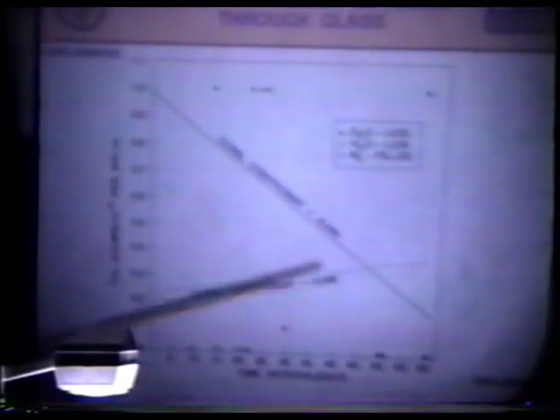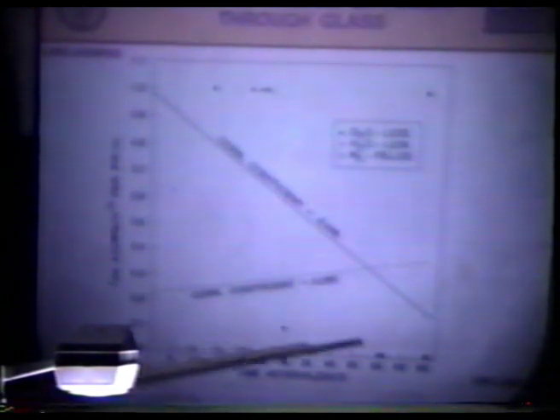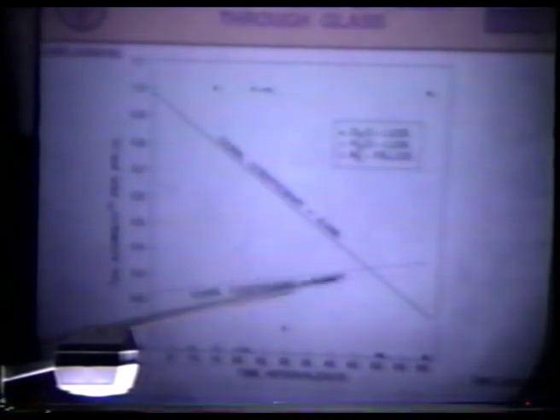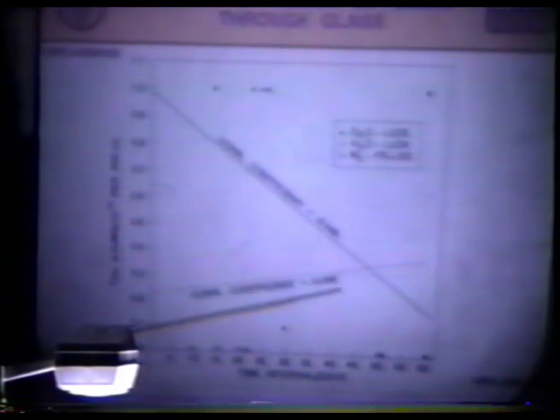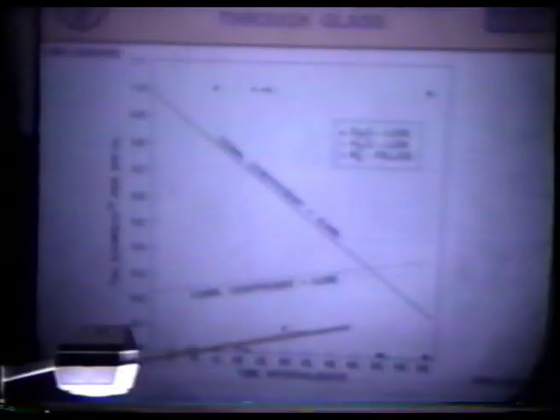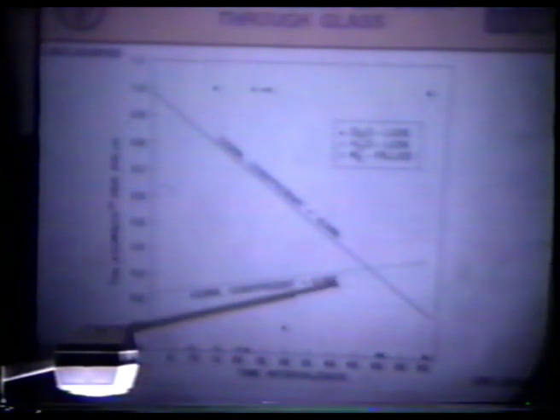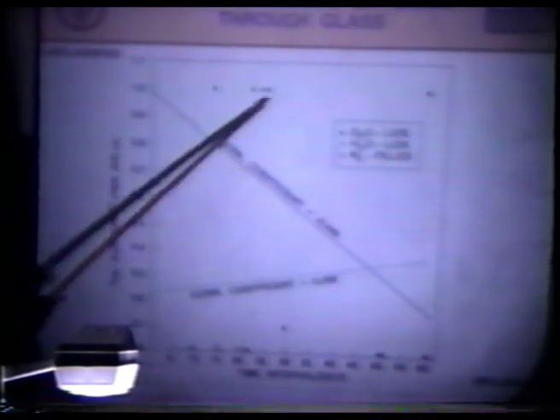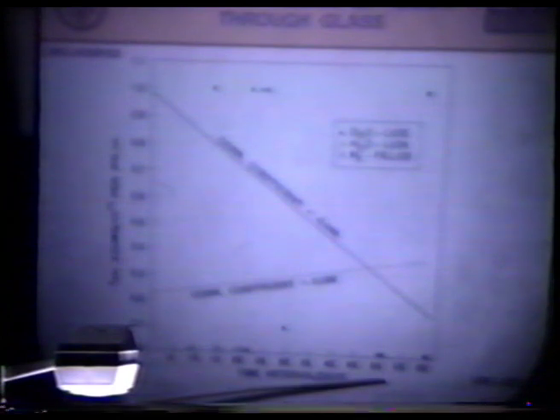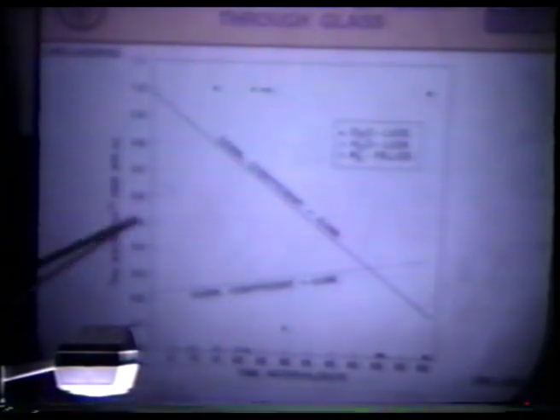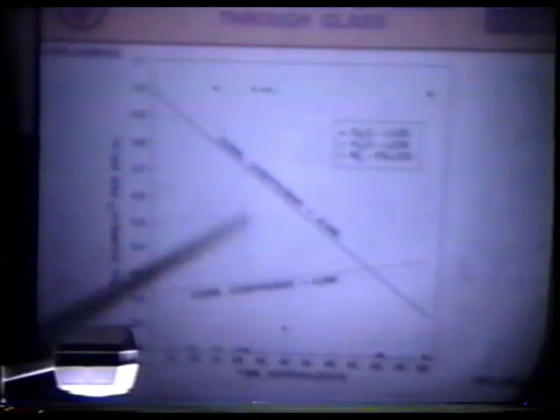We knew when the samples were collected, when I collected them in China Lake, and we know when the samples were analyzed in Texas. So we know how long these samples sat between collection and analysis. The longer they would sit, if helium were diffusing, you would expect to get more helium as time went on, if it were diffusing from the air into the flask. This is our D2O experiments. This is the time that the flask sat where helium may have diffused in versus how much we found. These are the D2O results, the dark circles. They're scattered all over the place.